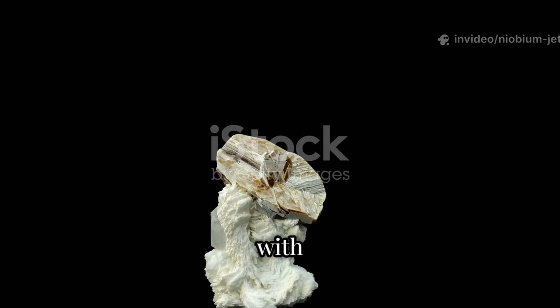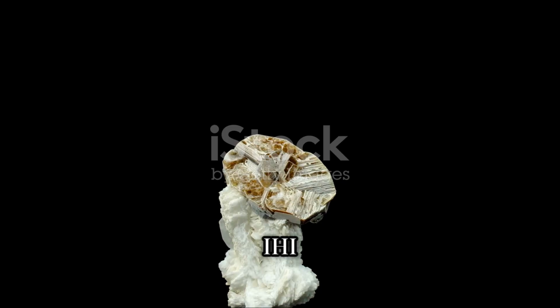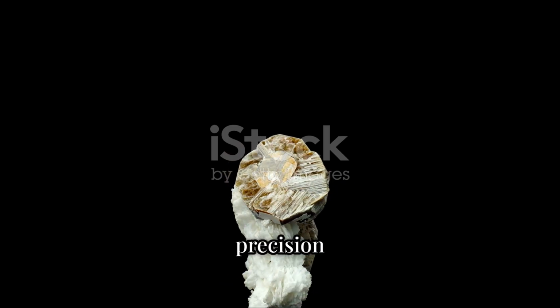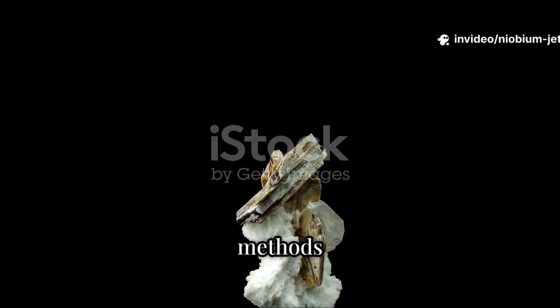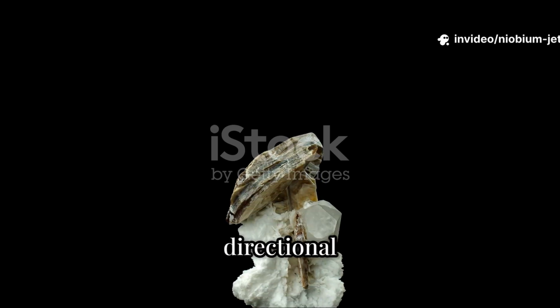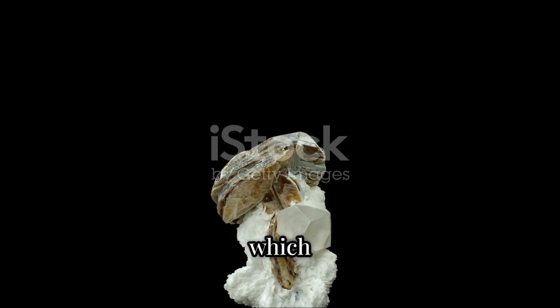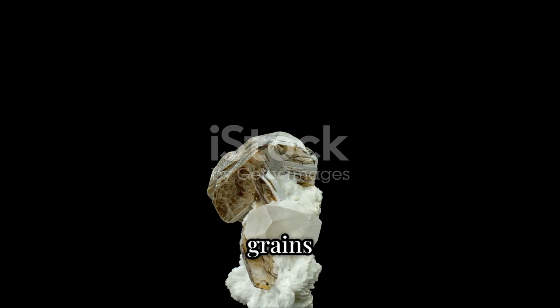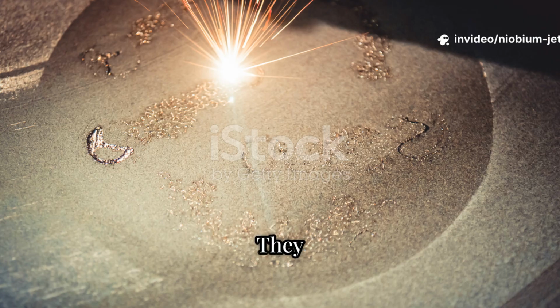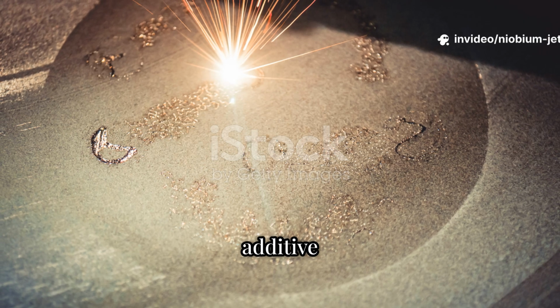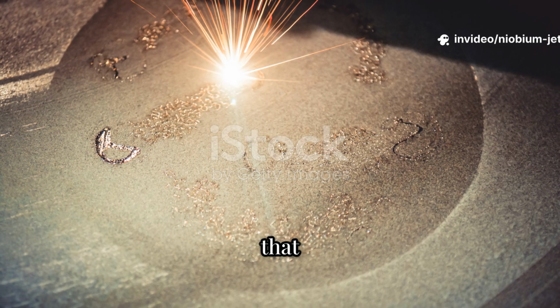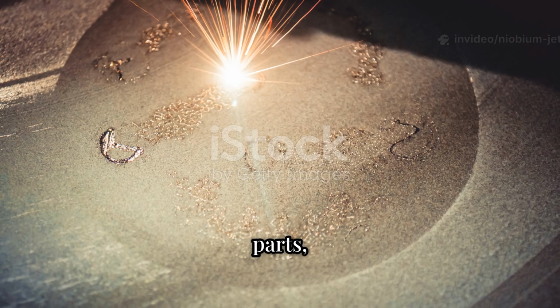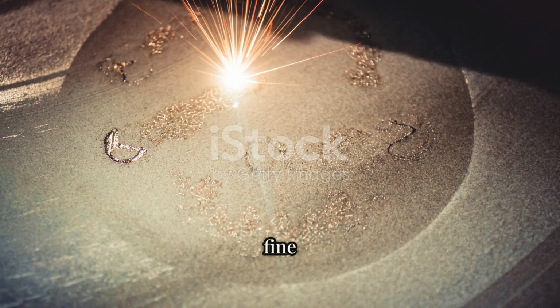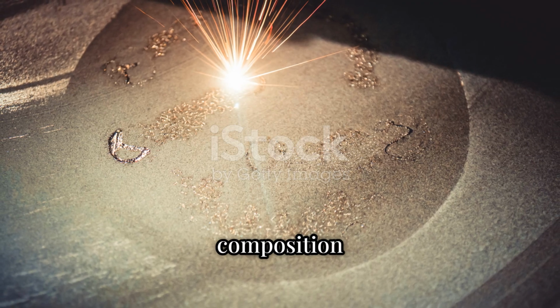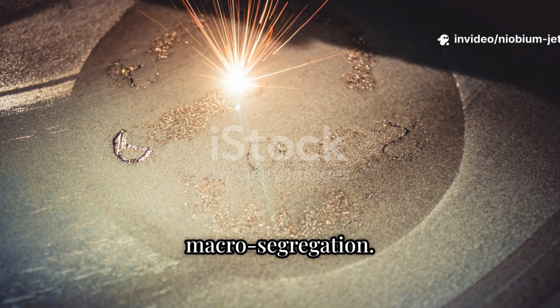As a certified company with vast experience in turbine engineering, IHI has advanced production technologies for precision casting and additive manufacturing. For parts like turbine blades, they master methods such as single crystal (SC) and directional solidification (DS) casting, which control the crystallographic orientation of the grains to maximize creep resistance. They are also actively exploring laser additive manufacturing (LAM), a technique that allows them to create near-net-shaped parts, reducing the need for machining and obtaining a fine microstructure with a uniform chemical composition distribution, which reduces macro segregation.